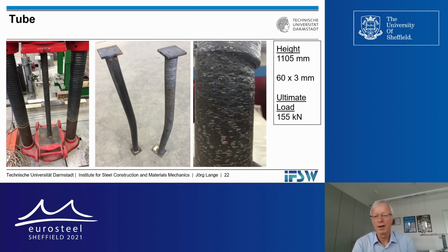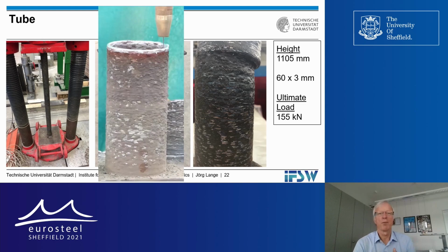We also printed some larger structures here. You can see a tube, approximately 1 meter high, 60 millimeters diameter, 3 millimeters wall thickness. In the center picture on the left-hand side, you see a normal hot rolled tube, and on the right-hand side, you see the 3D printed tube. Here you can see the printing process again in a time-lapse movie. I think you can do this if you need some very special geometry, as I showed it in one of the first pictures. If you have not a normal round or rectangular tube, but if you want something with 6 or 7 corners and all kinds of things, then it might be interesting. But here you have quite long printing times.